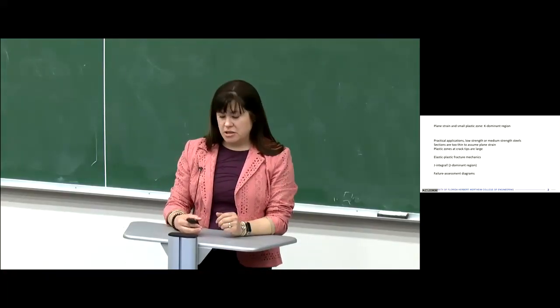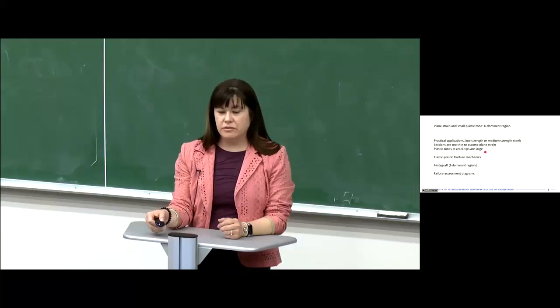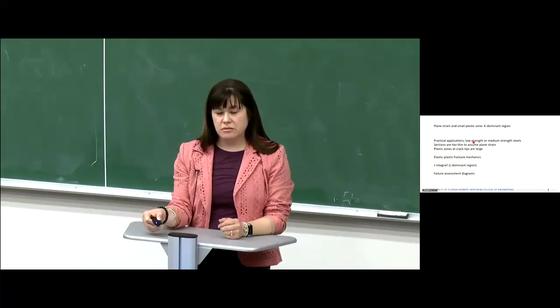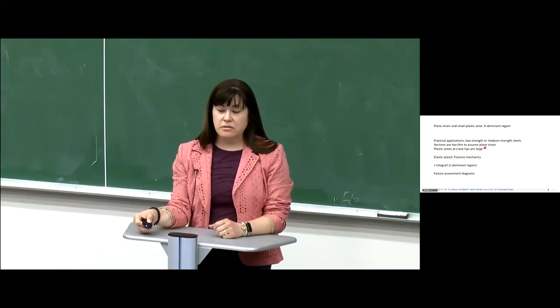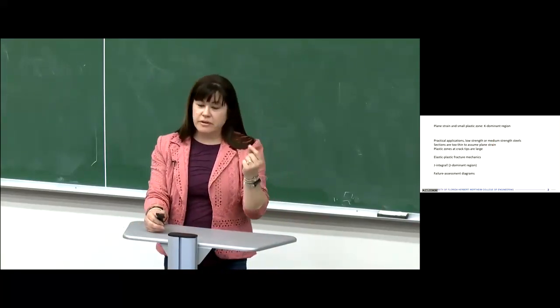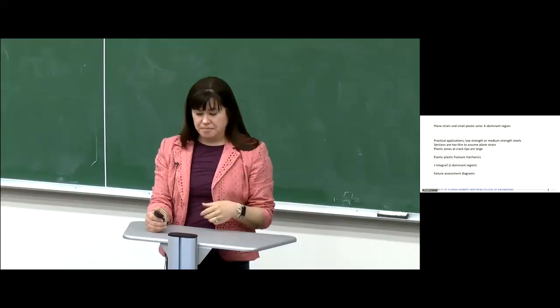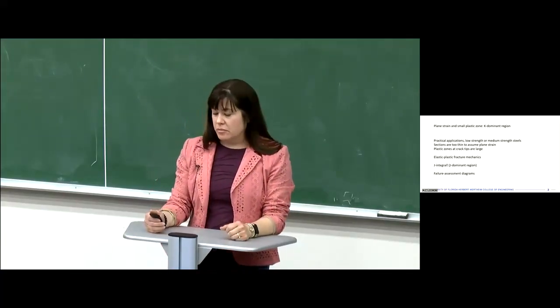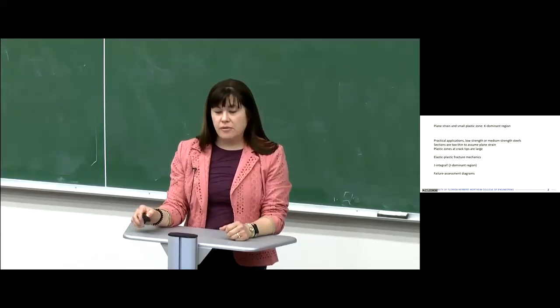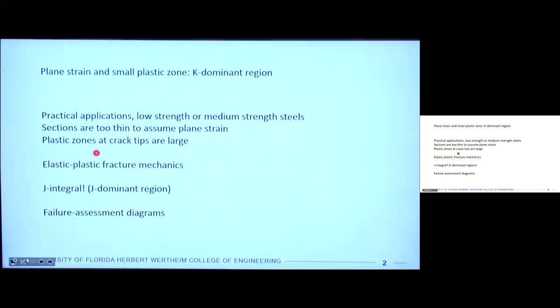But for practical applications, we may not have materials that have that high of a strength, right? So in practical applications, we may have low strength or medium strength steels, and the sections are too thin to assume plane strain. So we may have like a pressure vessel, thin plates, something like that, that are riveted together. And so we can't make that assumption anymore. And when we do that, that means that the plastic zones at the crack tips can be quite large. And so we can't assume that those plastic regions are very small compared to the rest of the material. And so that's where we come in with elastic plastic fracture mechanics.